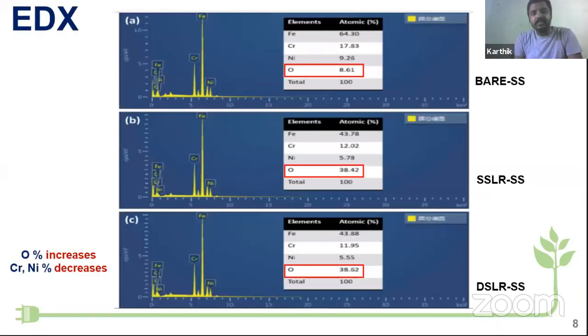Next one is EDS analysis. So the as-fabricated laser textured material has been subjected to EDS analysis. From this graph, we can identify that the concentration or percentage of oxygen is increasing, which is highlighted in the red box. So we can see from figure A that bare stainless steel has only 8% of oxygen, whereas single side and double side have nearly the same, about 38%. So the oxygen percentage is increasing, which reveals that during laser radiation, oxidation takes place.